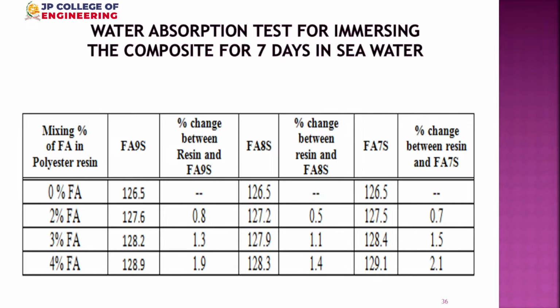We went for water absorption. So for water absorption, you see pure resin is good because it will not absorb any water. The surface is almost tightly sealed. Therefore we could not see any water absorption in the pure resin. But the moment you add particles, there will be small voids between the particle and the resin, through which moisture gets entrapped, and then the absorption increases.